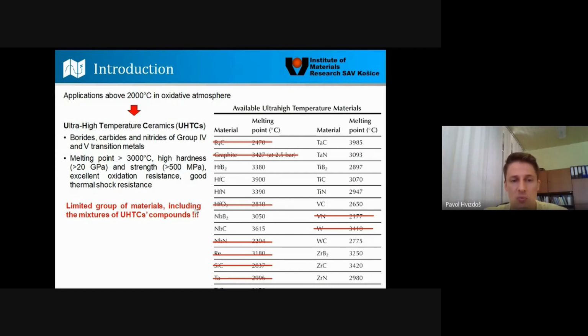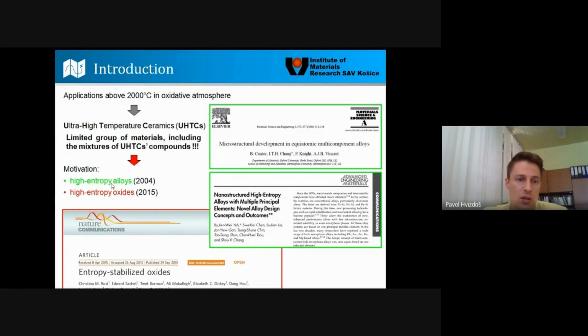So the thing is that we have a limited group of materials, and of course we can mix them, we can make compounds or composites from them, but they are still limited. So we were looking for some materials which can extend that limited group of materials, and the motivation came from high entropy alloys. Those materials are well known from 2004, and the concept of how high entropy alloys are formed was basically the motivation of the development of high entropy oxides, which were first produced and published in 2015. Up to that time, no one knew if it was simply possible, because it was thought that probably high entropy ceramic materials could not be formed in a stable single phase form. But in 2015, it was shown that it exists and can have some interesting properties.